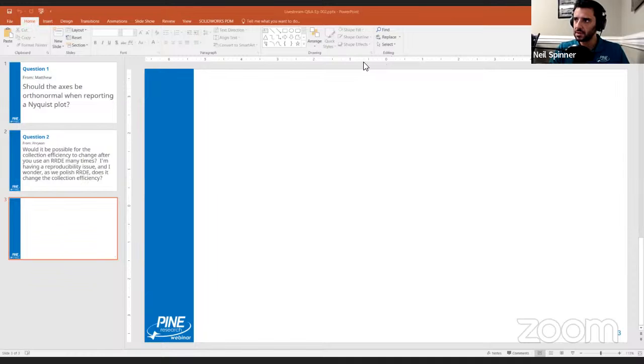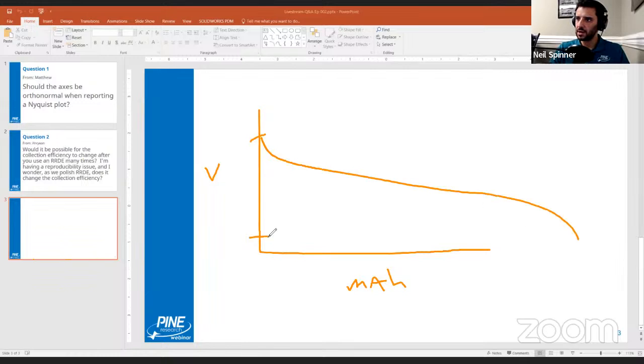So this question might be over and above if you're not really familiar with batteries. But essentially your first charge discharge, if you're looking at capacity like milliamp hours versus voltage, your first discharge might be out here, and then the rest of the charge discharge will be over here. So this is two things. The first is that it's SEI. When you build a battery from scratch and you do your first charge or your first discharge, the SEI usually hasn't formed yet. And so the first discharge curve isn't real in some sense as it relates to the steady state function of the battery, because the SEI being formed